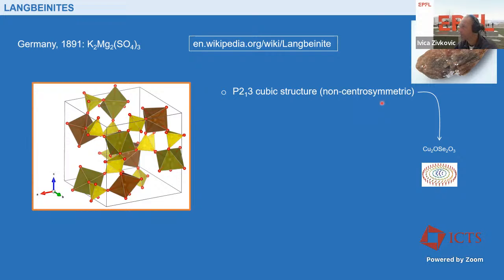Maybe the most important part is that it's non-centrosymmetric. And basically, this is how we actually ended up investigating langbeinites, because we were working on this skyrmion compound, copper oxoselenate. And then we were looking at other magnetic ion-carrying structures with the same space group. And then we stumbled upon the langbeinites.